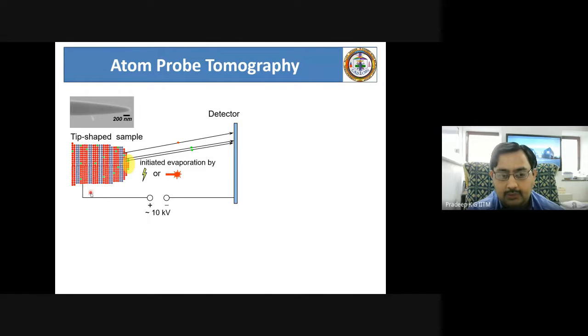That means, in addition to the positive potential on the sample, you apply negative potential to the detector, and you in principle apply either voltage pulsing or laser pulsing. That means for each controlled pulsing step where the base potential is active on the sample, the polarized atom becomes an ion. That means it gives one electron back to the sample and becomes an ion. And because we have negative potential on the detector side, all the positively charged ions are attracted towards the detector. That means you get a straightforward line projection from the origin of your atom into a projection imaging of an ion, and therefore you will be able to get a magnified view in 3 dimensions of all the atoms that are present in your material.